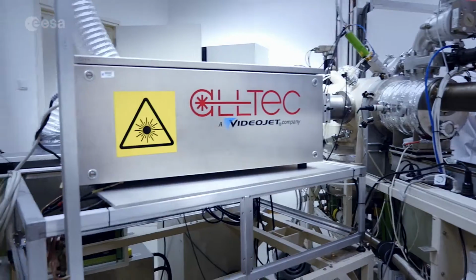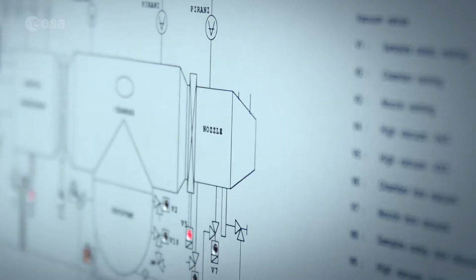Atomic oxygen isn't easy to produce on Earth. To generate the atomic oxygen, we use a high-energy carbon dioxide laser, and we focus this laser beam into molecular oxygen, and this produces an oxygen plasma. The oxygen plasma then expands into a vacuum chamber and accelerates the atoms onto the materials which we want to test.